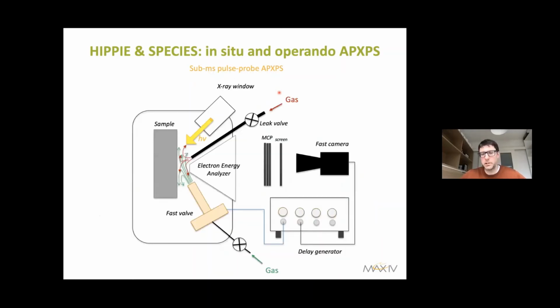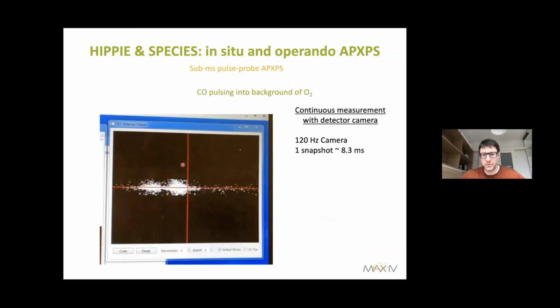With a small modification, we can now leak a second type of gas directly to the sample constantly, and then pulse the first gas to study their interaction on the surface. The reaction of choice is CO oxidation, obviously, on platinum in this particular case, because it's fast and quite easy to control. The video you can see here demonstrates this type of experiment.